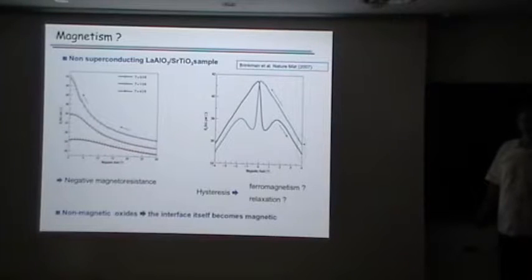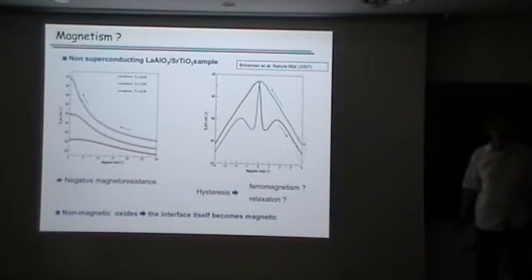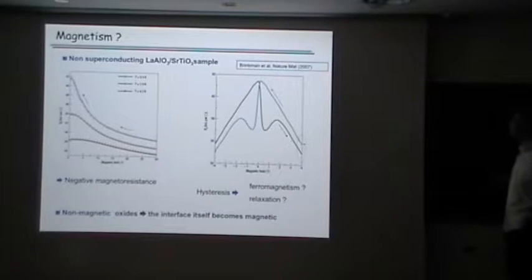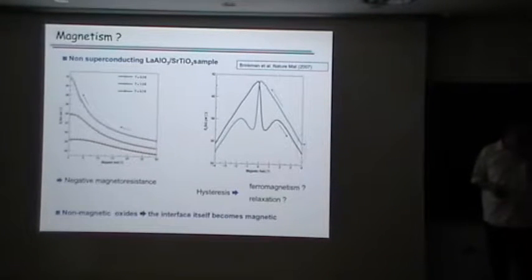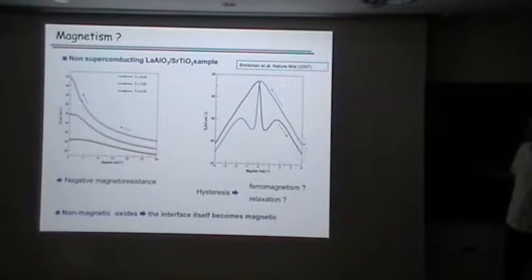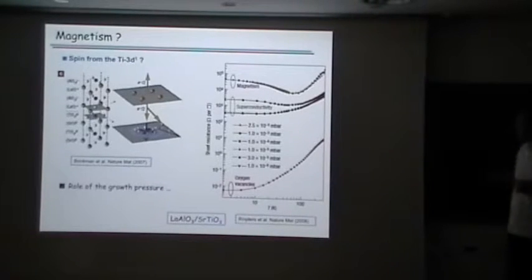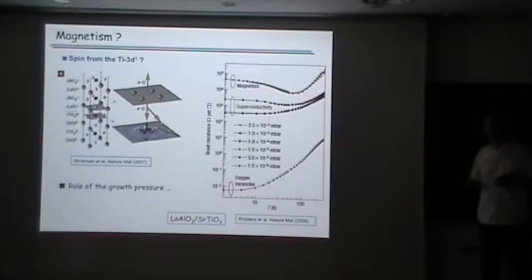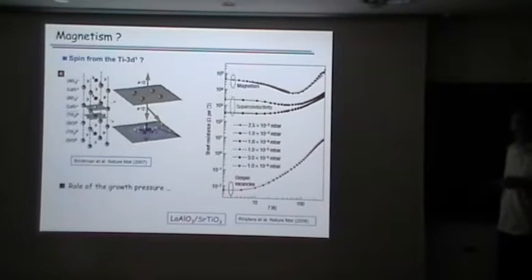The second order you can look for is magnetism. This is also in those systems controversial. This is a paper from Brinkman et al. in 2007. They observed negative magnetoresistance when they put a modest magnetic field, and they see some kind of magnetic hysteresis. So they say, okay, maybe we have some magnetism in the system, that was on lanthanum aluminate on strontium titanate. And they have arguments saying that maybe during this reconstruction I was talking about, in this system you may have some free spin coming from the titanium, and they order, and maybe there is a true magnetism in it.